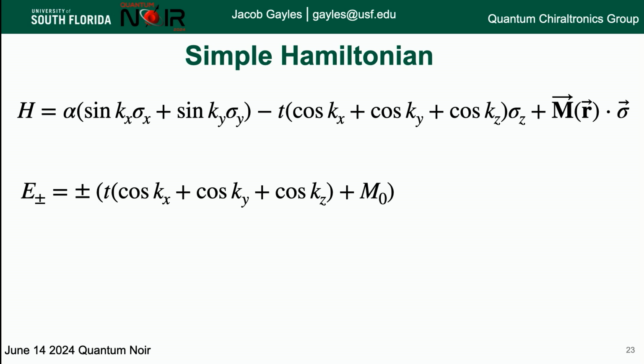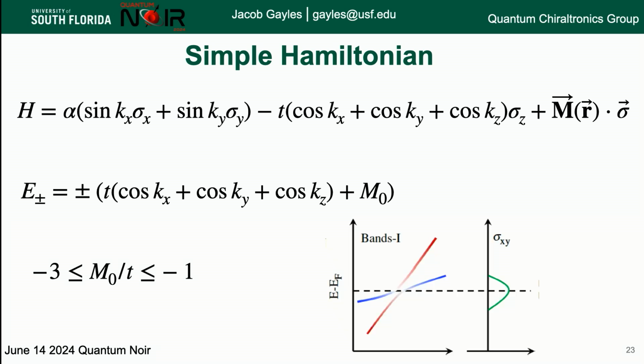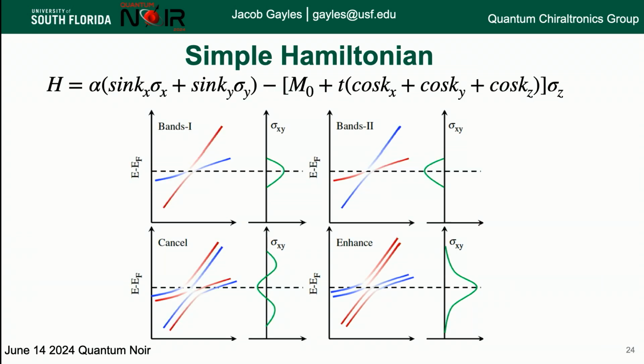And if I look at it along the path in kz, then I can get the cases where it always has to have this degeneracy of this Weyl point, which is bounded just due to this arc cosine here. And what happens here is when it's bounded and has these degenerate crossings, you produce an anomalous Hall effect directly at those crossings. And it's chiral here, so if I switch the chirality, then I switch the sign of the anomalous Hall effect. So that's what happens here.